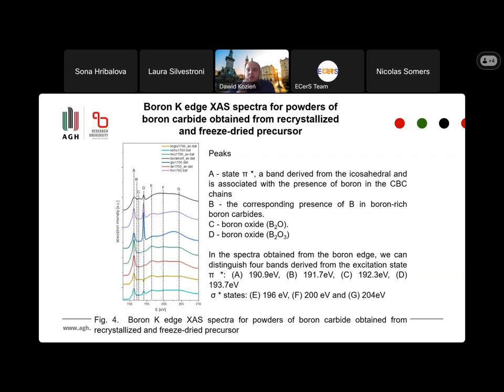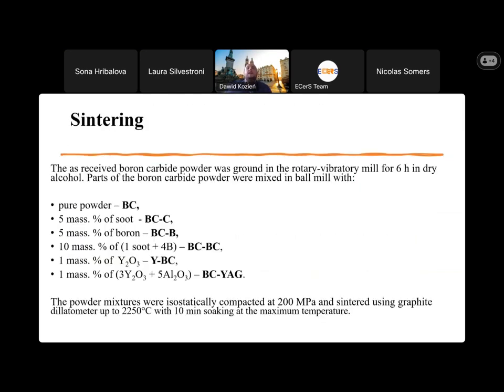In this research, we checked that every boron carbide, whether synthesized by us or bought commercially from another supplier, has a very thin layer of boron oxide. Maybe this can be seen here. This layer is very important because it gives a liquid phase during the sintering, and you can manage the reactive sintering using the liquid phase. Of course, we have some results on this, and I can mention my journey with the sintering of ultra-high temperature materials at the SAS Institute in Slovakia in Professor Dusza's group, a great time with the guys in this group, Ivan, Tamas, Victor, and the others.